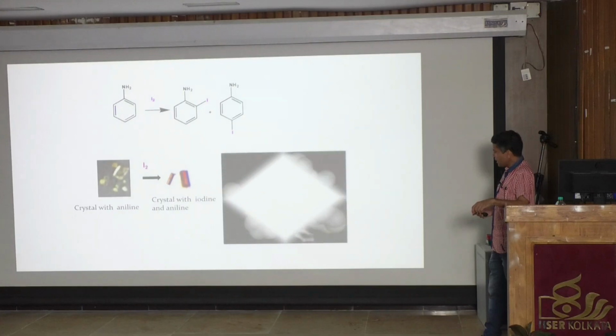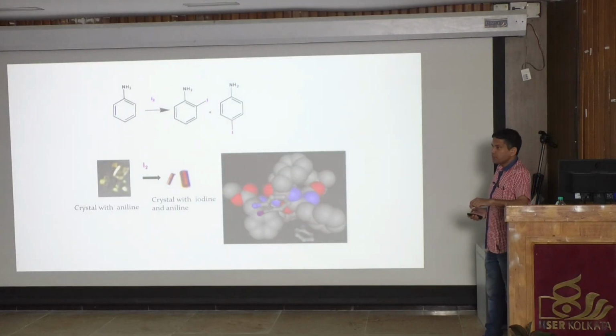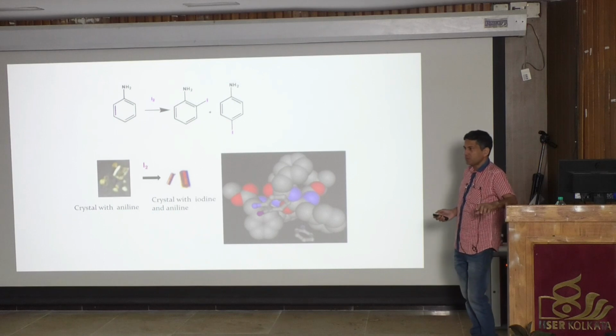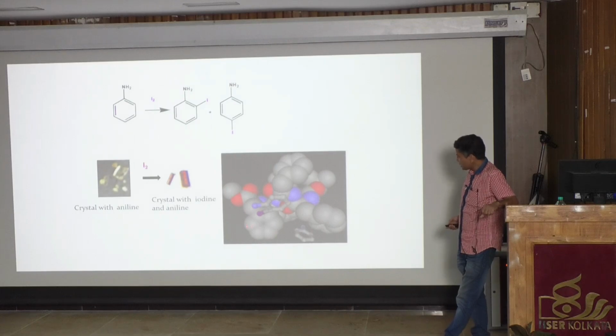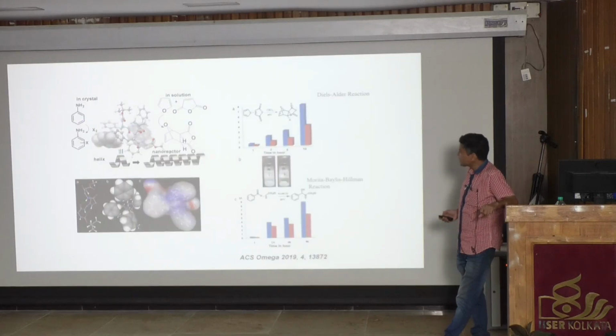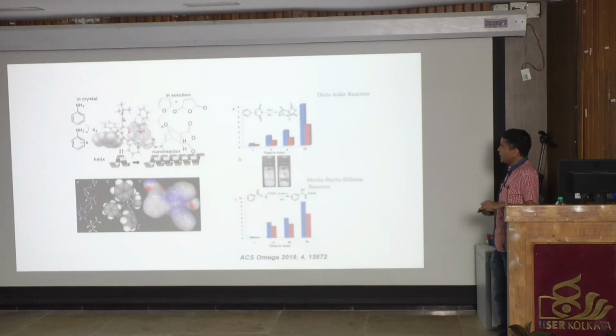After exposure to iodine, the crystals are very bad in shape. There is a huge amount of iodine absorbed over the crystal, but we were able to take data. The data is not very good, but we figured out the position for iodination, because of the particular position of this compound inside the channel. We have also done other reactions using this kind of nano reactor, like the Diels-Alder reaction or the Morita-Baylis-Hillman reaction, and this is what we find inside the channel.